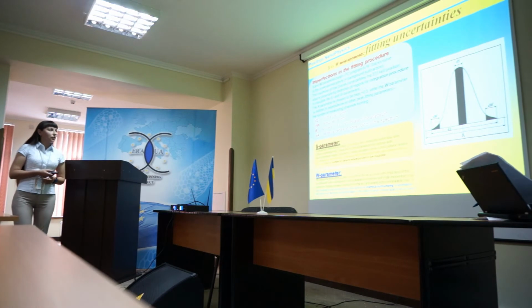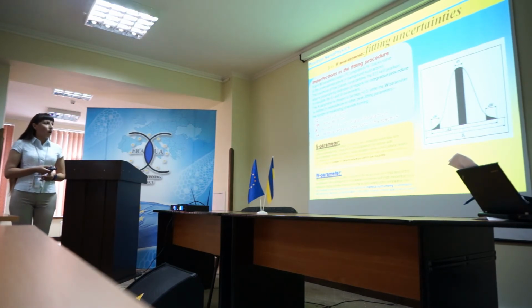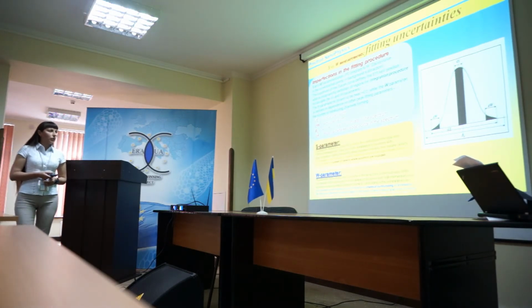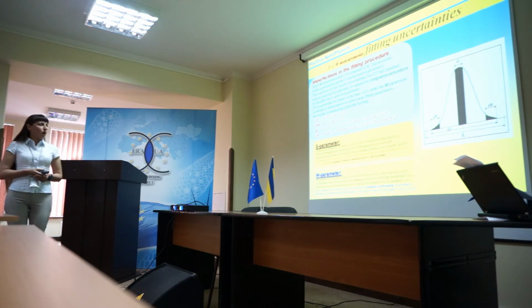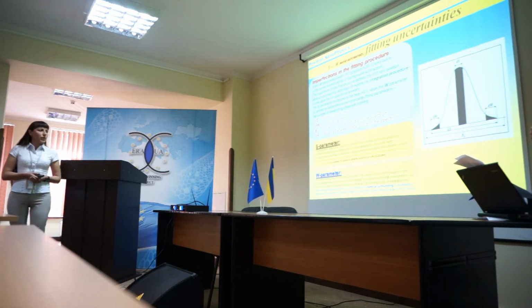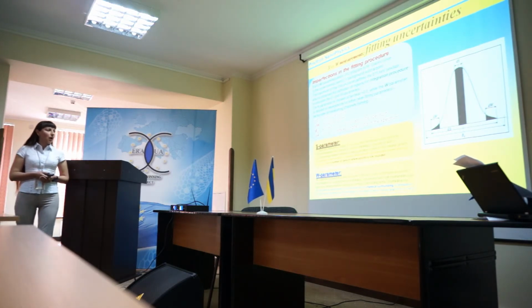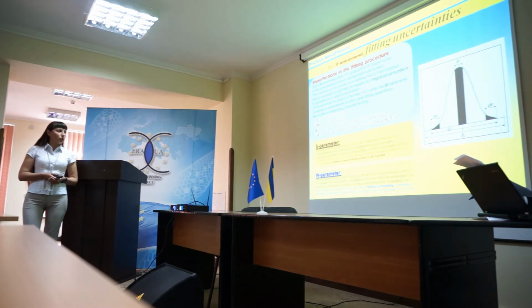S parameter is defined as a ratio of counts in the central part to the total area of the annihilation line, and characterizes the annihilation of positrons with low momentum valence electrons. W parameter is defined as a ratio of counts in the wing part to the total area of the annihilation line, corresponding to annihilation of positrons with high momentum core electrons.